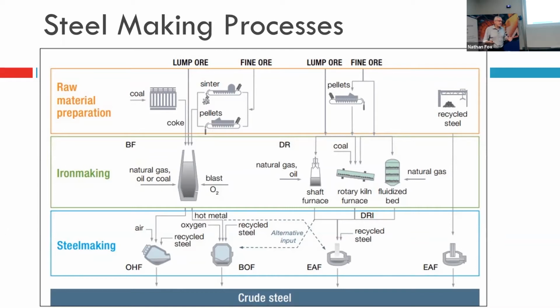The basic oxygen furnace is a process where you blow oxygen into a molten bed of iron, and that reduces the carbon content of that iron so that you can make steel. Pig iron has about 3 to 4% carbon, and normal structural steel is 0.1, 0.2% carbon. That was Bessemer's discovery, removing carbon from iron to make steel, way back.